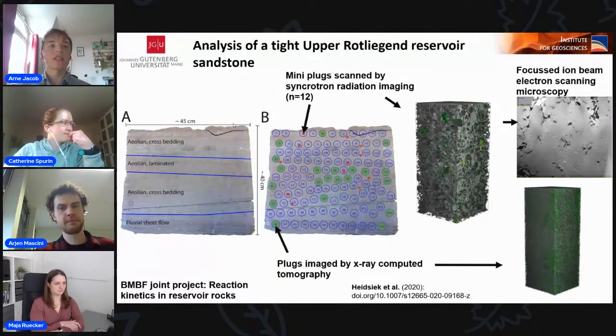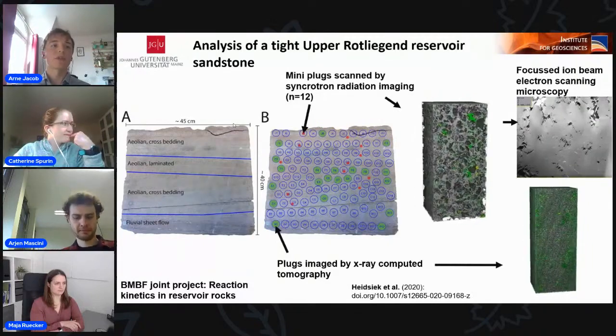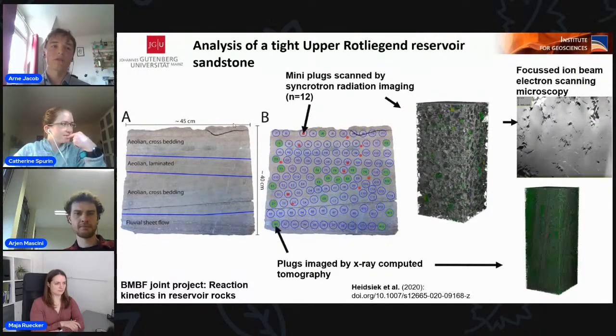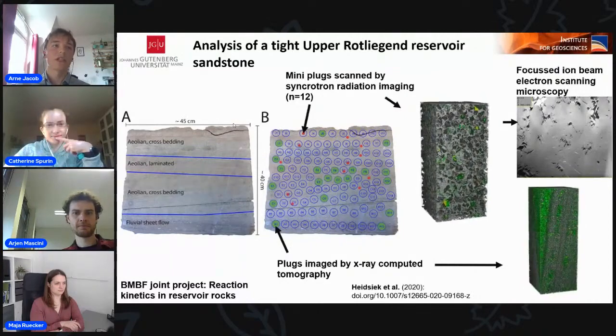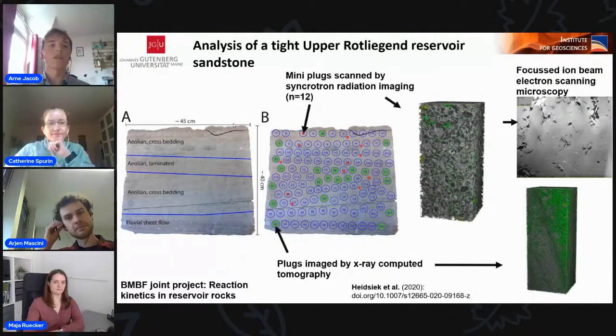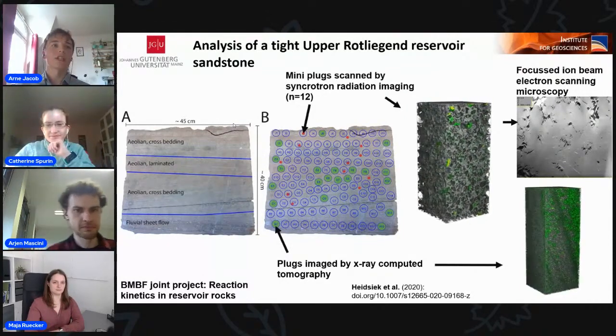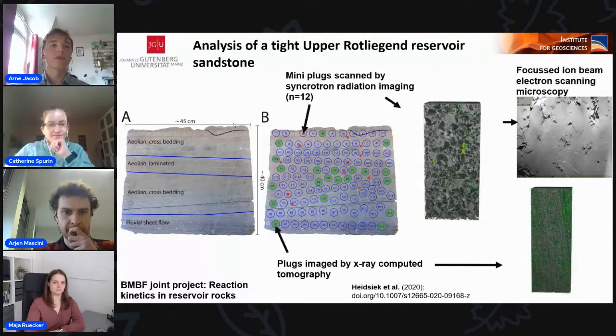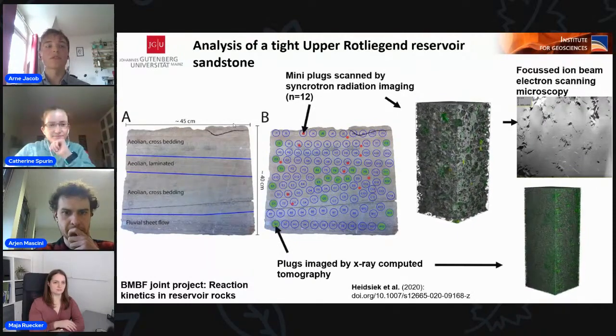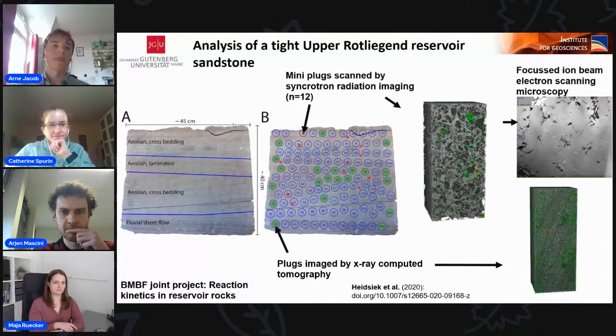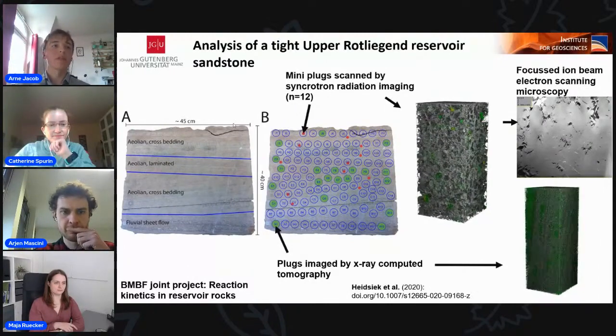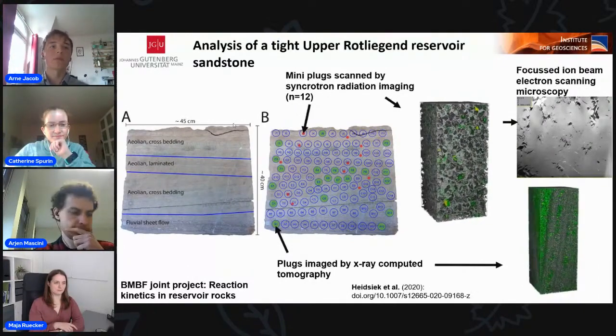On the right-hand side, you can see our sampling locations where we drilled plug cores with a diameter of 2.5 centimeter in green and mini plugs with a diameter of 3 millimeter. We used the larger plugs for conventional microcomputed tomography and the smaller plugs for synchrotron computed tomography. We conducted the scanning of the mini plugs at the DESY facility in Hamburg.